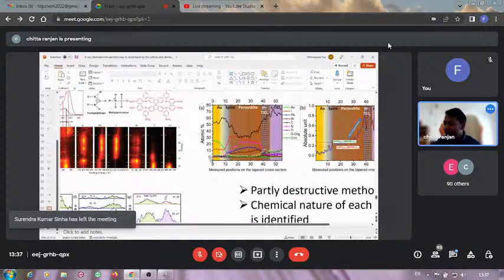And you can see in this region only the lead, lead, bromine, iodine, chlorine, each has higher concentration, and in other places it is low concentration. That means it shows that this is perovskite, this is gold, this is titanium dioxide, and this is also another kind of titanium dioxide. So from here we can see different parts, and from there you can say, okay, which element is present with which. Here we found it's a combination of bromine and iodine, and here mostly bromine and iodine, and here it's a higher amount of bromine. So this is something we can say, okay, what's happening over there.